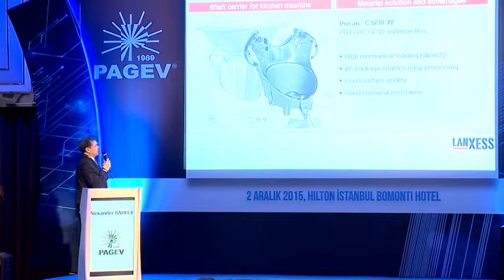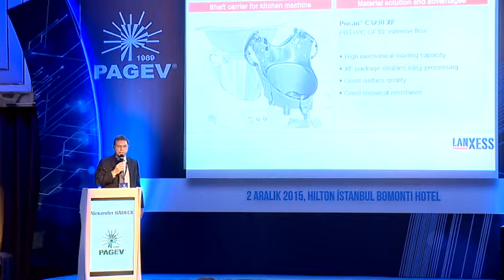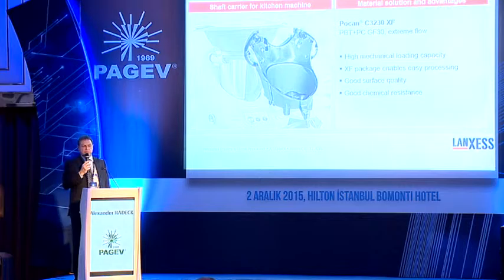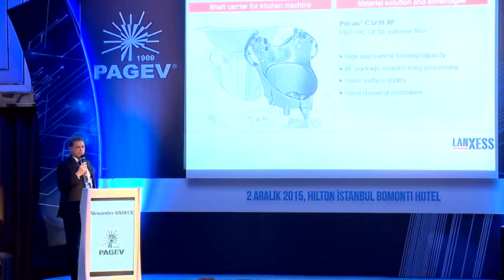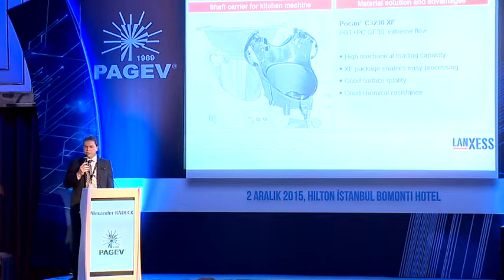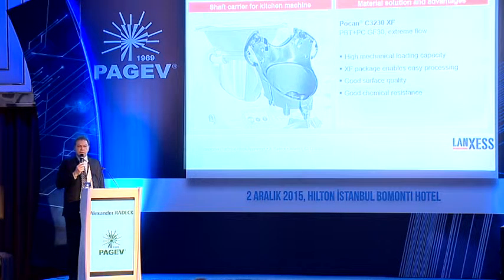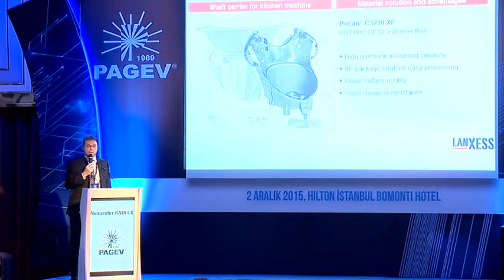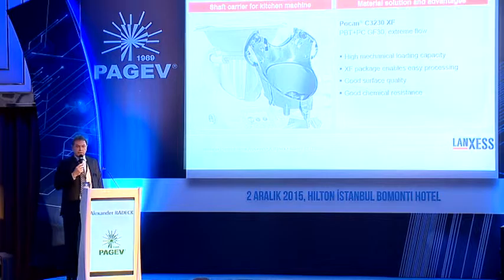In this case, the choice was a PBT PC blend with 30% glass fiber, and in this application it was a formulation that also had an easy flow package included. With this one we could fulfill the demand on the mechanical loading. With the easy flow package we could significantly improve the flowability of the compound, which also led to a good surface quality. The inner part, despite being an interior part, is visible as soon as you lift up this metal container. So there has been a specific wish to have a good surface quality.